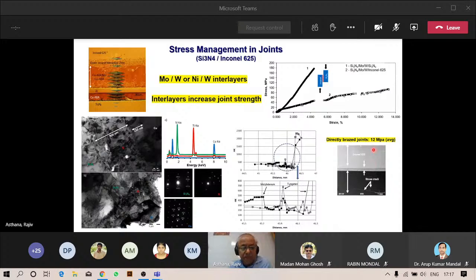So many people have shown that you can manage stresses using multilayers. For example, you can put moly tungsten or nickel tungsten or other combinations in this joint region. So you have to select the thickness and the expansion properties. Also, the elastic modulus compatibility should be there. So we came up with these combinations for silicon nitride bonded to Inconel. And this is an example of a braze called copper ABA, which contains basically aluminum, silicon, and titanium. The main constituent is copper. This is a commercial braze commonly used in industry.